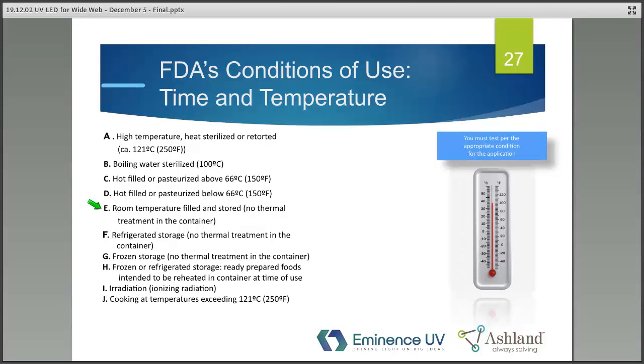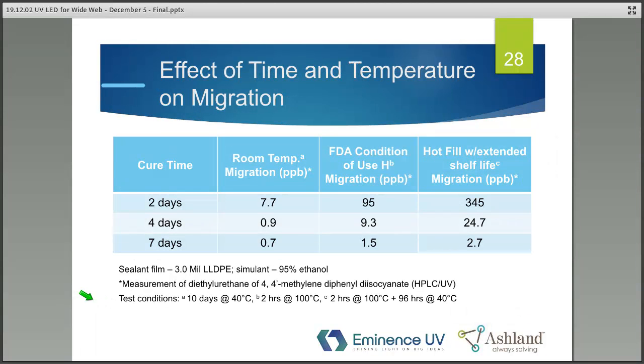If you had a product which you wanted to do a microwave test to see if it could be microwaved, if it was a frozen food or refrigerated food, you could use condition of use H, which is 2 hours at 100 degrees Celsius. But again, you want to match your conditions of use to how the food is going to be used. And then here at the bottom, you have cooking temperatures. Basically, anything above 121 degrees Celsius. The FDA recommends that you test the product at the temperature the food is going to be exposed to and for the duration. So if you have something that's at 350 degrees Fahrenheit for 2 hours, you would test at that. So what are the effects of time and temperature?